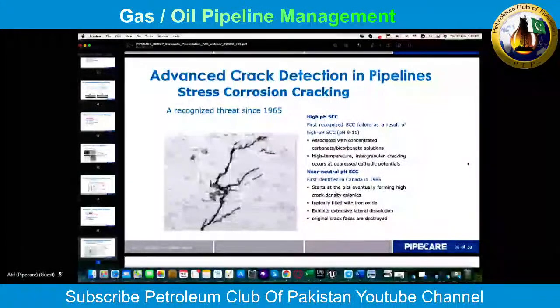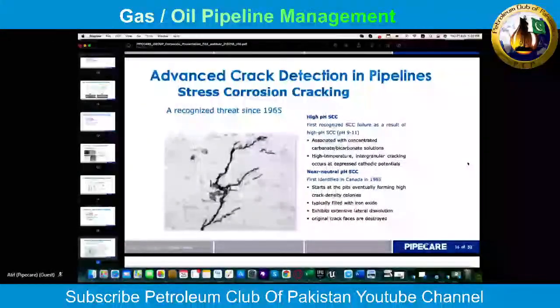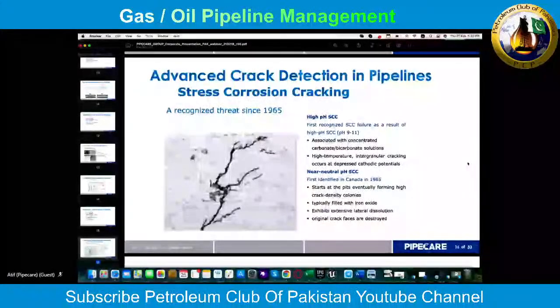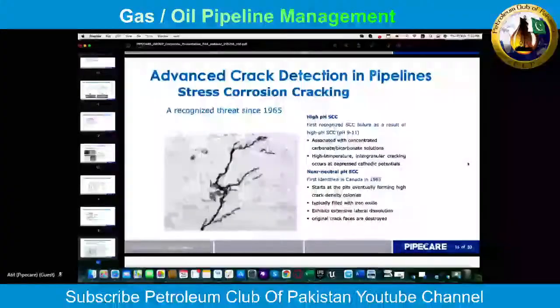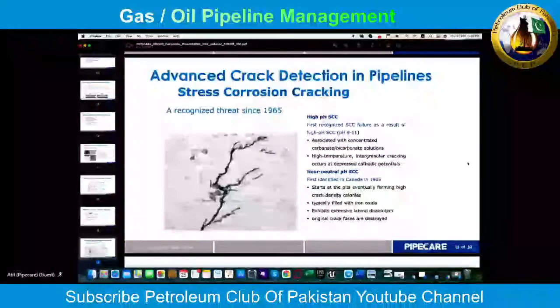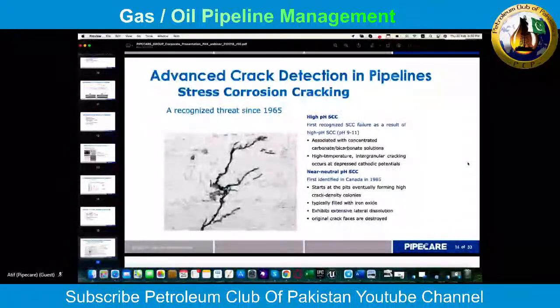The most dangerous is not the single crack, the most dangerous is the stress cracking colony, where several cracks are building and all of a sudden they are growing together, and this contributes to that exponential growth of a crack. And if cracks merge, suddenly the pipe wall is not that strong anymore and bursts. The other type, which was first identified in 1985 in Canada, is near neutral pH SCC.